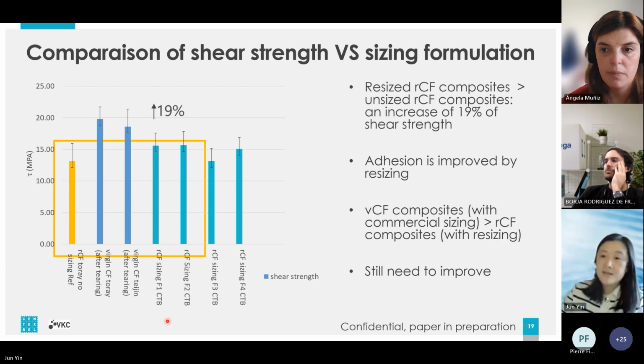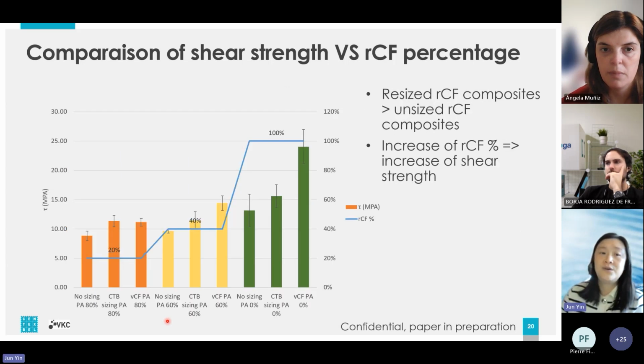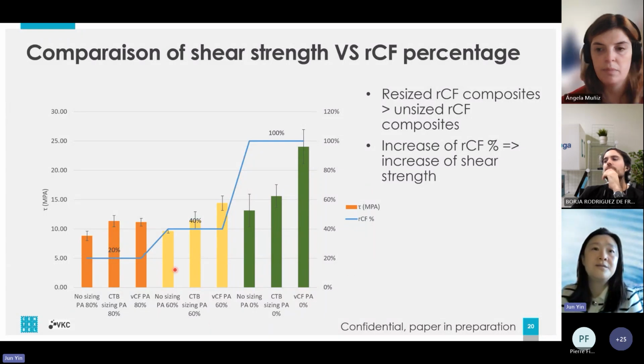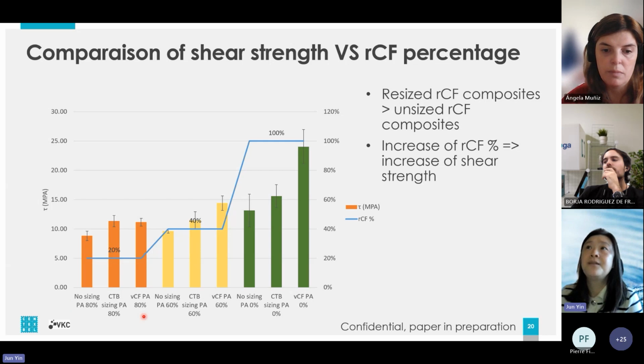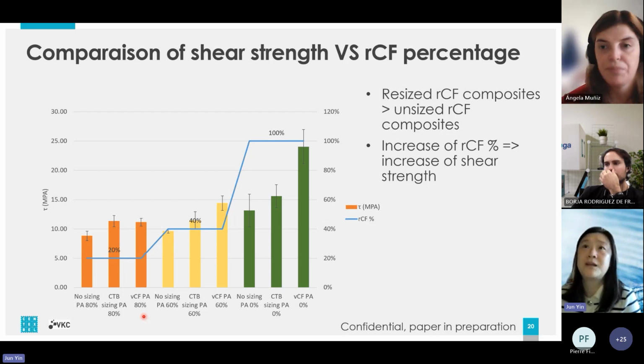So if you remember, we also tested the different percentages of carbon fibers in the nonwoven structures. So here we compare the 20%, 40%, and 100% of recycled carbon fiber. Again, if we compare within one kind of composite, we can prove again that the resized recycled carbon fiber composite has a better shear stress than the unsized recycled carbon fiber composite, and also with the increase of the carbon fiber percentage, there's an increase of shear strength.